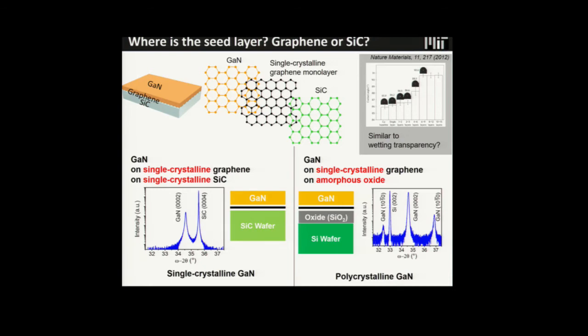Also, in a similar time frame, there was a publication in Nature Materials. If you drop water on graphene on a substrate, the wetting angle can change depending on the underlying substrate. That kind of gave us a hint. Maybe the underlying substrate could be the seed layer for growing single crystalline gallium nitride. Maybe graphene doesn't do anything in this epitaxial process. So what I did was simple. We peeled off single crystalline graphene from the silicon carbide. Then we transferred this single crystalline graphene onto amorphous oxide. Then we performed the epitaxial growth of gallium nitride. If graphene is really the seed layer, you are supposed to still get single crystalline growth, even if this graphene is on the amorphous phase. But the result was quite shocking.